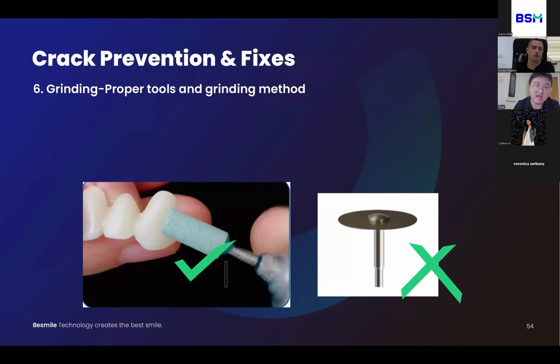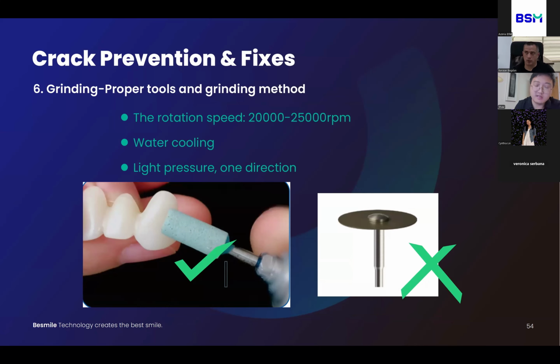And when we grind the crown after sintering, there's also something we need to pay attention to. When we grind, it will generate a lot of heat in the grinding area. So we need to do cooling during grinding. We need to prepare a bottle of water, and before we do the grinding, we can immerse the restoration in the water, and then take it out to grind. So on the grinding area, the temperature won't be that high. And after the restoration gets drier, you can immerse it into the water again. In this way, you can cool the restoration well during grinding.